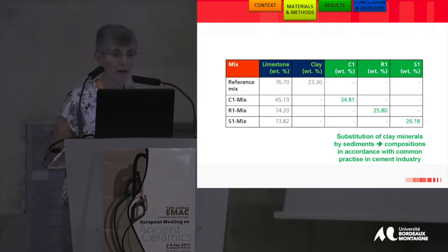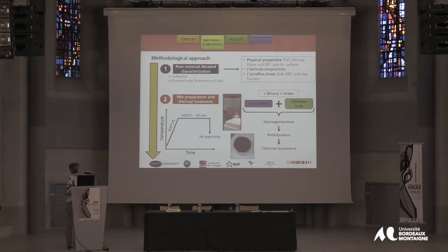So what did we do? We first started with characterization of the raw materials, the sediments and the quarried rocks, using techniques like particle size distribution—which has to be below 100 microns in our case—density, specific surface area measurements, chemical composition through X-ray fluorescence, determination of crystalline phases by XRD, or a specific study of the clay fraction.